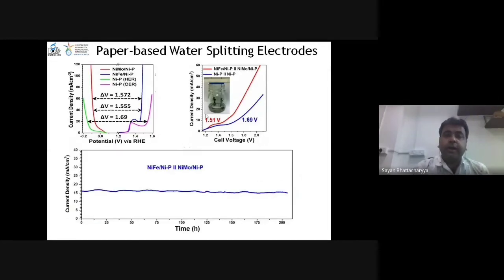And if you connect the anode and cathode, you get a complete water splitting, and you can do it at 1.51 volt with the catalyst. The nickel paper itself also can do its job. It is 1.69 volt, very stable over 10 days, I must say, of continuous operation. So, which is very nice.